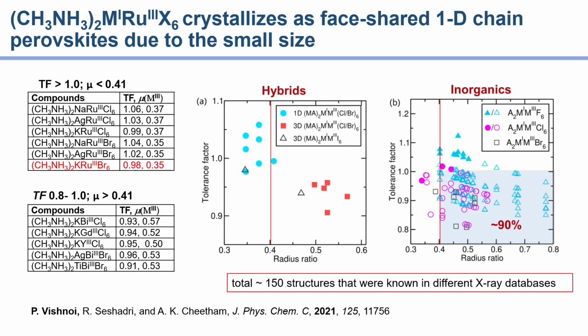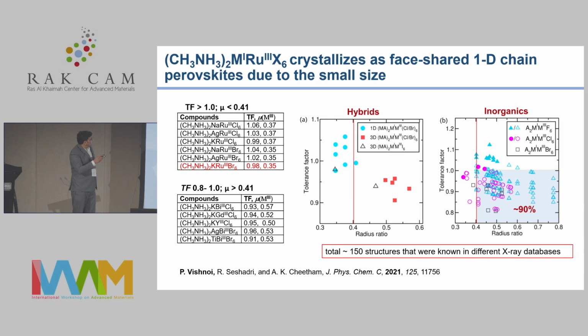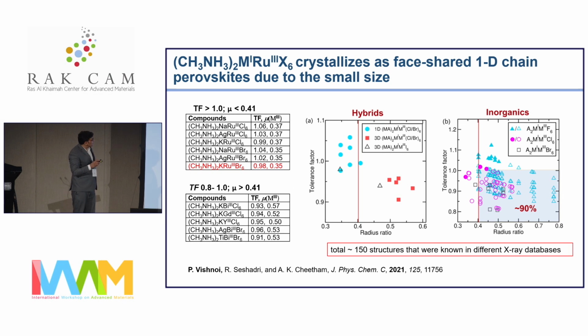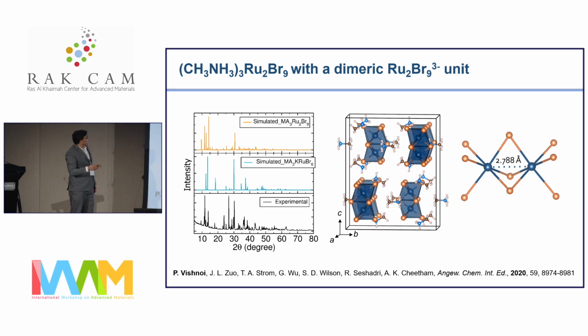One of the things you notice here is that as we increase the 1+ cation size, the tolerance factor becomes more appropriate for a 3D structure. And this is the only case where we get a mixture of compounds, 1D plus a 3-2-9 phase. This indicates that when one of the two parameters is appropriate for 3D structure, the chances are high that the compound is trying to form a 3D structure, which is becoming more favorable over a 1D structure. However, many times when we try to form a 3D perovskite, this 3-2-9 phase becomes more favorable over the 3D structure. And that's the reason we are getting a mixture of two phases.